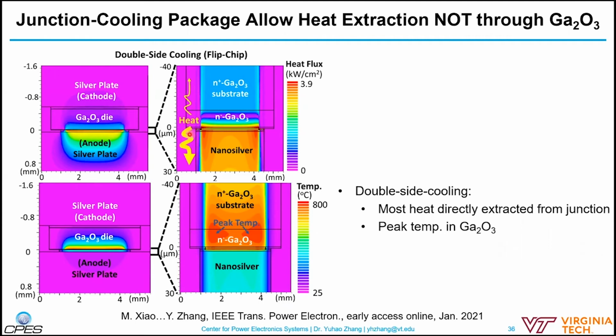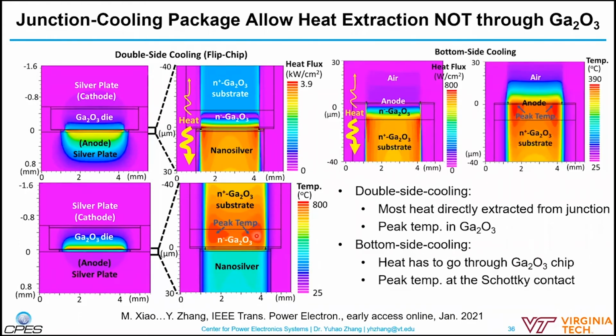So basically, we can see most of the heat is extracted directly from the junction, and very little is extracted through the upward path, which goes through the gallium oxide substrate. And if you look at the peak temperature, it is now within the gallium oxide. In comparison, this is the bottom side cooling, where the anode is on the top. Almost all the heat has to be extracted going through this very high thermal resistance gallium oxide substrate, and the peak temperature is right at the Schottky contact.